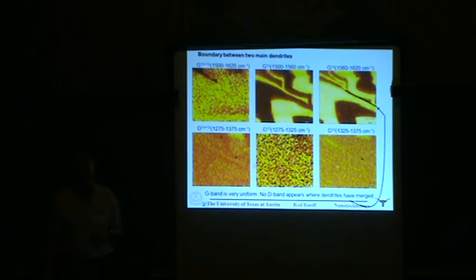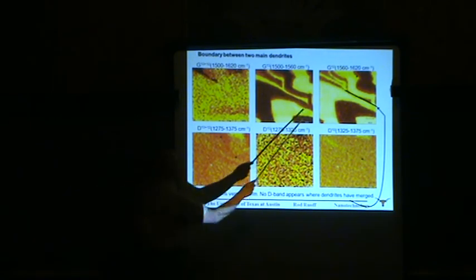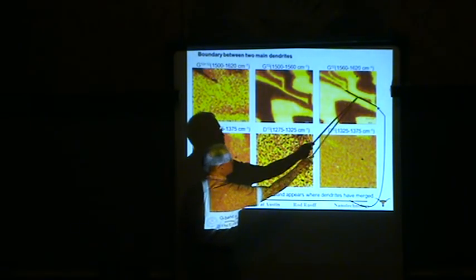Do we have a defect along that line, and therefore many defective regions as this grows? Or does it somehow join in such a way that we have perfect hexagons along that line? One way of evaluating that was to do this isotopic labeling again and color code where the joining line is, so we can identify it very accurately. As I'm showing you here, this is exactly where that region merges.